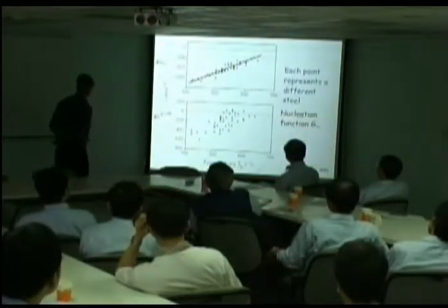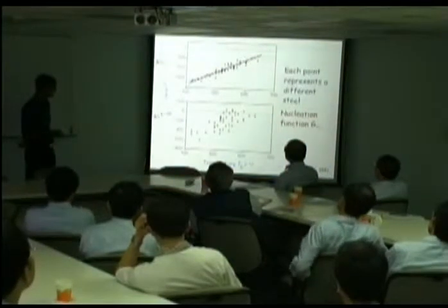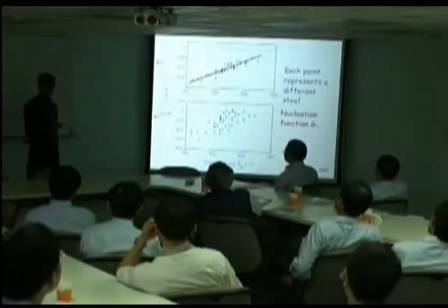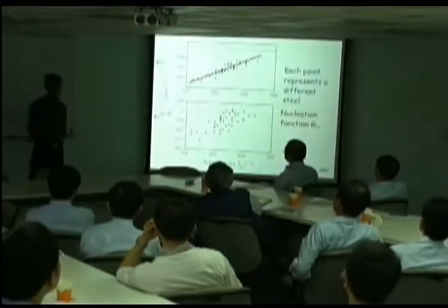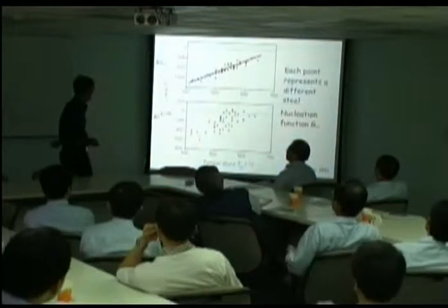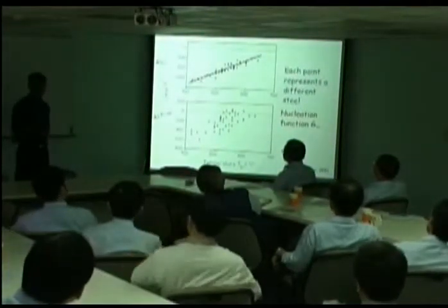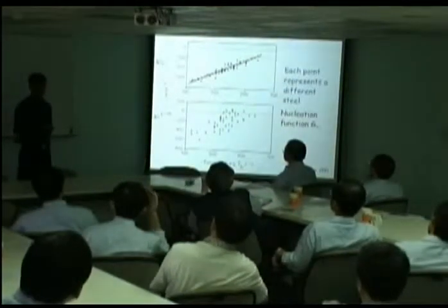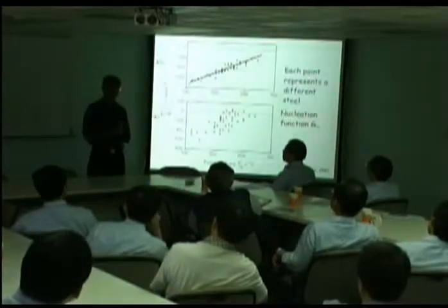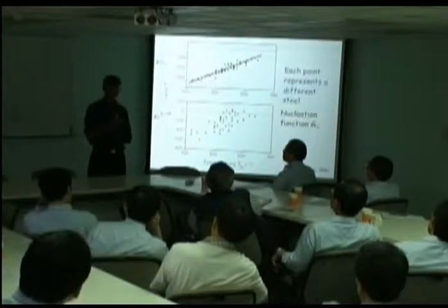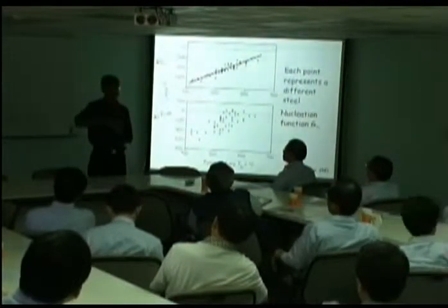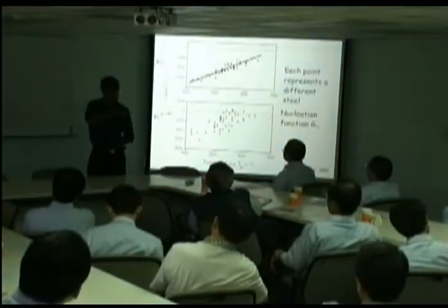Now, one thing you notice immediately is that, look, if I assume diffusionless nucleation, I actually get a positive free energy change in some cases, and that's not possible. You cannot have an increase in free energy during nucleation. So my conclusion is that during nucleation we must have the diffusion of carbon. And this is what distinguishes bainite from martensite. In the case of martensite, both nucleation and growth are diffusionless. And this is the reason why we see a C curve for bainite, whereas for martensite we have a straight line.